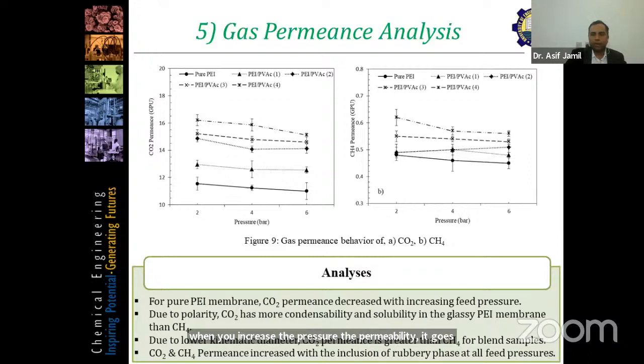And on the other hand, for CH4 permeance for the same pure polymer membranes, the trend is the same: as you increase the pressure, the permeability goes down. But the permeance of CH4 is very low compared to CO2. And this is because of 2 factors. Number one, polyetherimide has a higher affinity for CO2 because CO2 is a polar molecule. So the condensability and solubility of CO2 at the polyetherimide surface is very high.